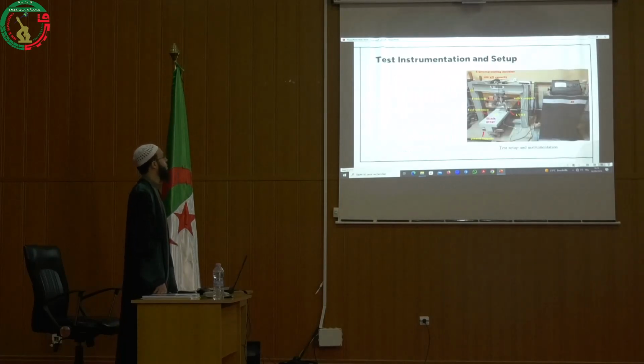Finally, our test instrumentation and setup was carefully designed to conduct a 3-point bending test. The 3-point bending test was conducted on a simply supported beam with mid-span loading and 900 mm clear spacing. Strain gauges and LVDTs were used to measure strain and mid-span displacements, with the load control method applied using a hydraulic actuator.